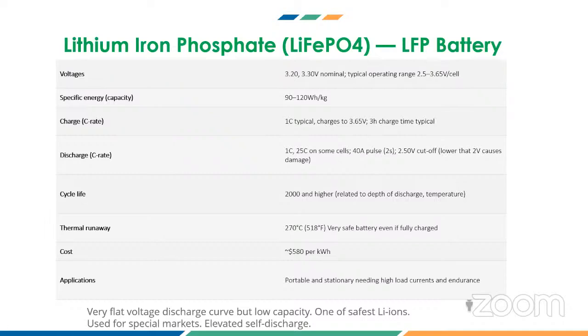And here also one drawback is the self-discharge. That means if you are not using the vehicle for a few days, it is very difficult to start the vehicle. That is one of the problems. So most of the scientists are working on this battery, lithium iron phosphate, to improve the electronic and ionic conductivity. The discharge rate is possible up to 25C, but practically it's very difficult. It has poor ionic conductivity. Because of that, discharging as well as charging is very difficult. So we have to focus on improving the charging rate as well as the discharging rate of the battery.